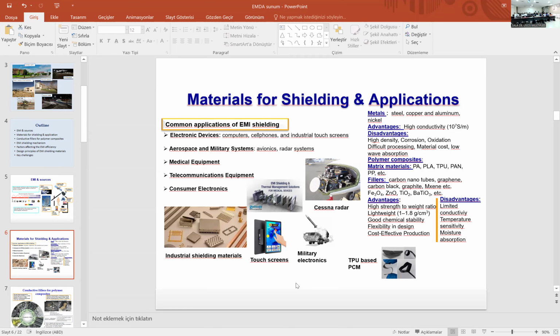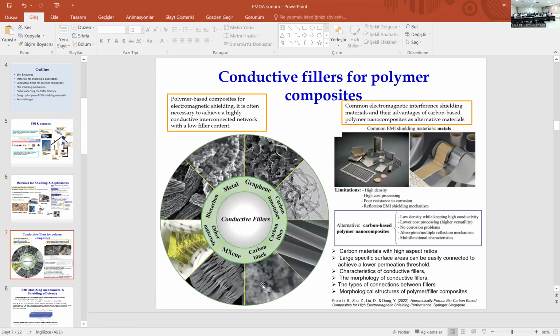Polymer composites offer several advantages compared to metal-based EMI materials, including being lightweight, low cost, more flexible, and having better wave absorber properties. The conductivity of the polymer composites can be provided by conductive fillers like carbon black, carbon nanotubes, graphene, graphite, and MXene. EMI shielding materials require not only conductive fillers but also high magnetic properties and dielectric constants, like magnetic materials. For polymer-based composites for electromagnetic shielding, it is often necessary to achieve a highly conductive interconnected network with a low filler content.